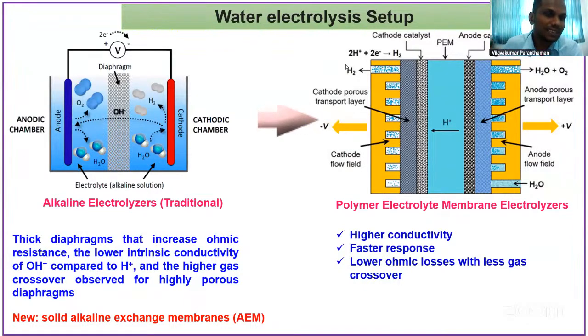See here the thick diaphragm, there is a lot of force, so the hydrogen and oxygen gases cross over, and the total experiment is spoiled. As well, the thick diaphragm has a high resistance, lowering the intrinsic conductivity. So compared to that one, PEM is the best one. Nowadays, recent work has explored using solid alkaline exchange membranes to improve the performance.